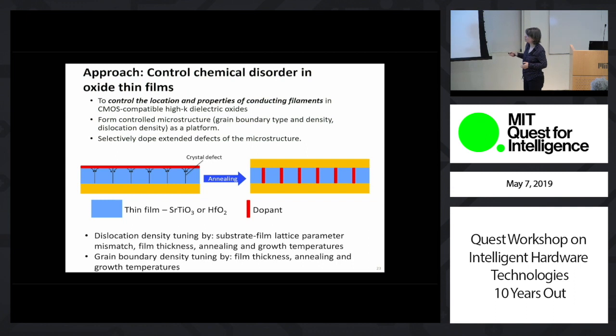And once that microstructure is prepared as a platform, we can further tune the local properties of those extended defects, such as grain boundaries in this case, by chemical doping. And depending on the dopant type, we can make these boundaries more favorable to switching consistency or less favorable to switching consistency. Okay, so I won't go into the chemical details. And we have started with hafnium oxide, and by varying the preparation conditions post-treatment, we are able to control the texture of hafnium oxide. Okay?